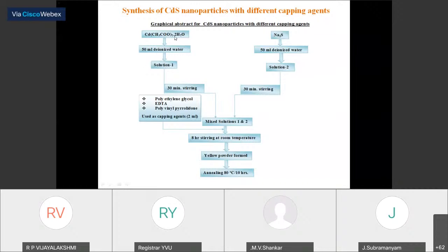To synthesize the cadmium sulfide nanoparticles, the raw materials we took in our laboratory were cadmium acetate as the cadmium source and sodium sulfide as the sulfur source. We dissolve them in deionized water, because the cadmium acetate is easily soluble in water.